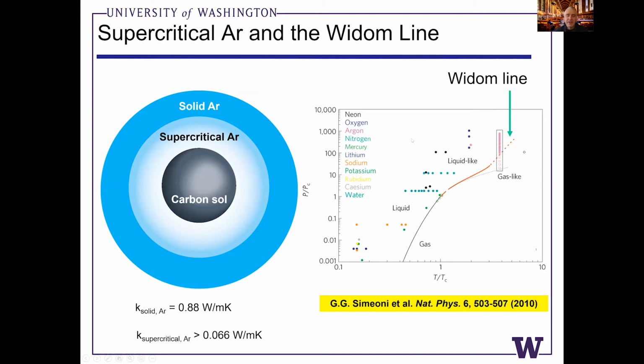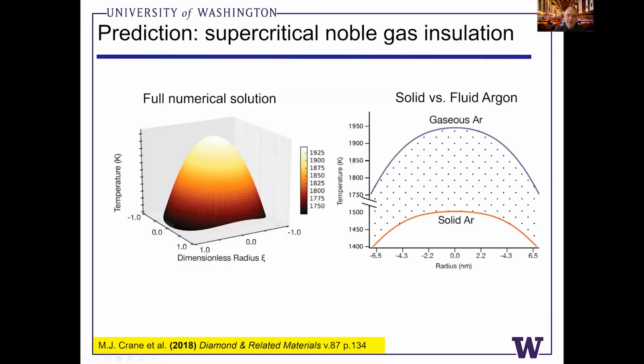And we can estimate from other molecular dynamic simulations that the thermal conductivity of supercritical, superfluid argon is about an order of magnitude less than that of the crystal. It just conducts heat less efficiently. So we did some numerical analytical calculations with these different thermal conductivities. And sure enough, if you plug in the superfluid conductivity, temperatures can jump to on the order of 2000 Kelvin. And if you start with solid argon, these temperatures would be on the order of 1400, 1500 Kelvin.